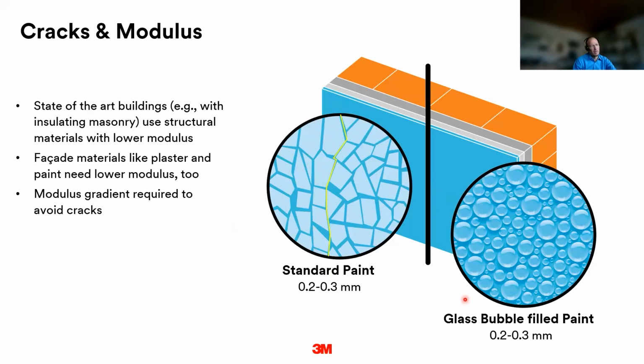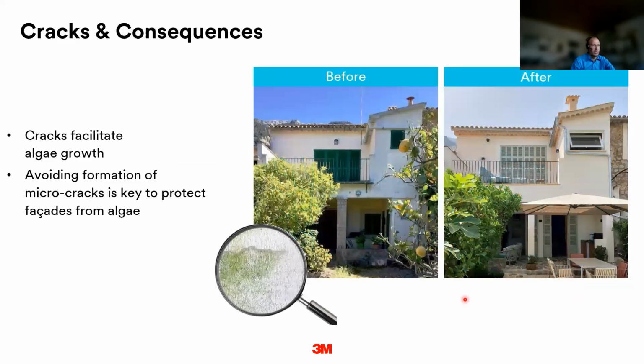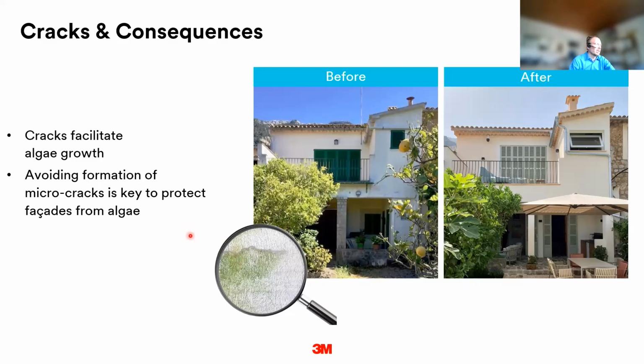The bubbles will decrease the modulus. So that means if there's some movement in the facade, the stresses are lower, and stress is also dissipated, and they're less prone to form micro cracks. And why is that important? Because these micro cracks are typically the beginning of evil, like formation of algae growth. And if we can avoid cracks, we also avoid other problems that can arise from that later on.